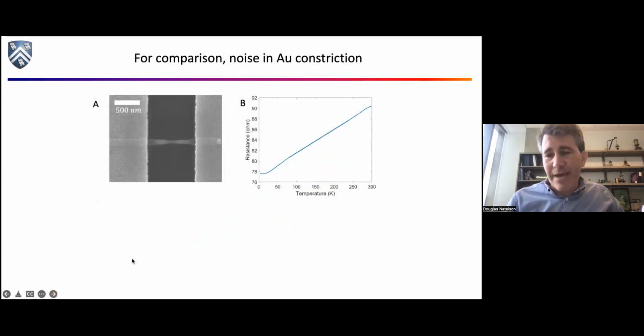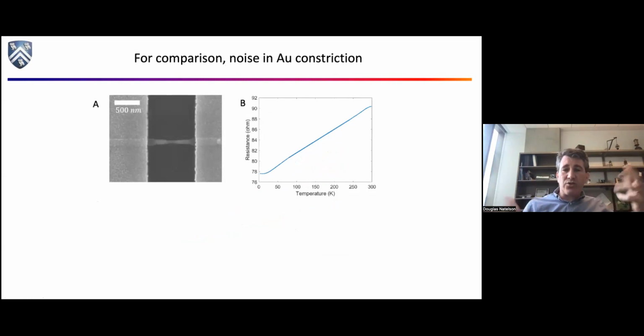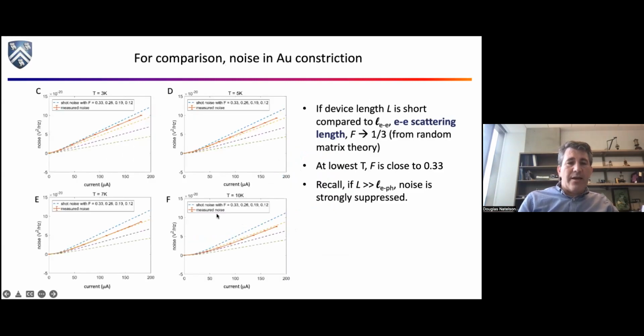Now, you might ask, maybe this is just something weird about our measurement setup, right? So let's do the control experiment. Here's a wire made out of gold. Same setup, very similar dimensions. Here's the resistance as a function of temperature for the gold wire. Hey, it looks quadratic at low temperatures, which it's supposed to. Resistance is actually rather similar. What happens in that system? Well, in that system, at 3 Kelvin, the Fano factor is about 1/3. Okay, and that's basically what you'd expect.